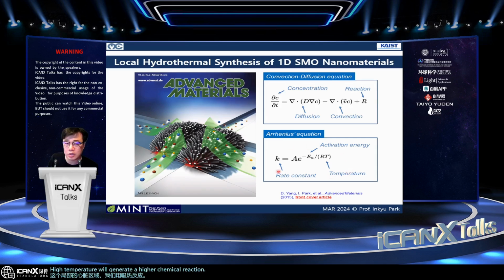So according to the Arrhenius equation, at the high temperature, we've got high chemical reaction rate. So these precursors actually react and form these nanostructures on the local hotspot. So using this process, we can do a direct synthesis and also simultaneously we can integrate these nanostructures directly on the electrodes for the sensors.